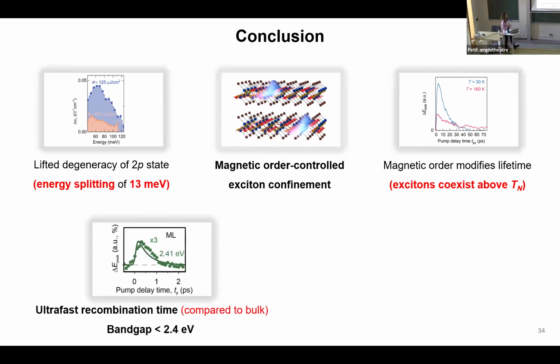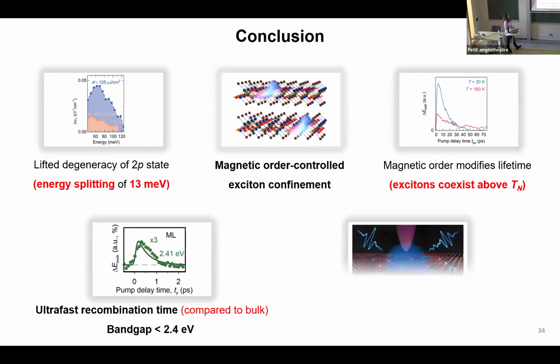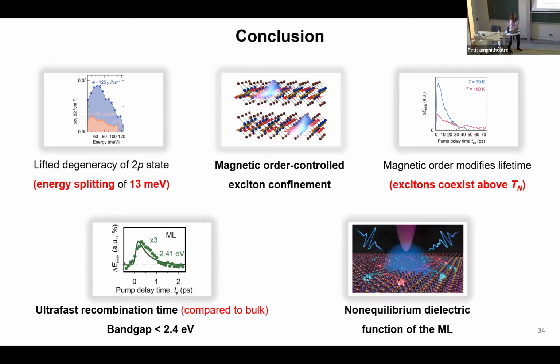In the case of the monolayer, we saw that the ultrafast recombination of the 1s exciton is an order of magnitude faster than what we observed in the bulk due to relaxation with defects and some non-radiative channels. And we understood an estimate of where the monolayer band gap should be, it should be at least smaller than 2.4 electron volts. And I showed you what we can get about the non-equilibrium dielectric function using ultrafast terahertz nanoscopy.